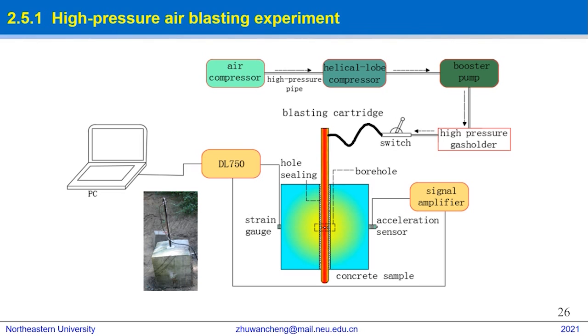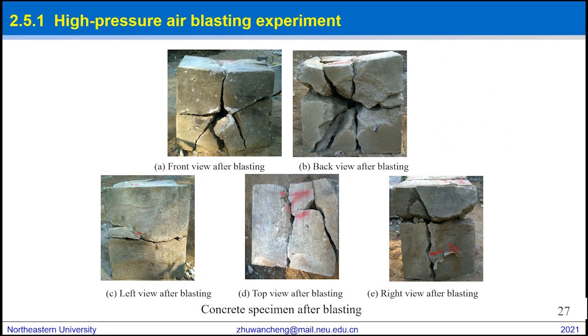Through a switch and pipe, the high-pressure gas holder is connected to the blasting cartridge which has been inserted into the hole. One type of high-strength gypsum is used for sealing the hole. As soon as the switch is turned on, the high-pressure air is sharply released, and it flows into the hole to fragmentize the concrete block. During the experiment, the particle vibration accelerations at the outer boundary of the sample are monitored. This slide shows the failure pattern of specimen after blasting.